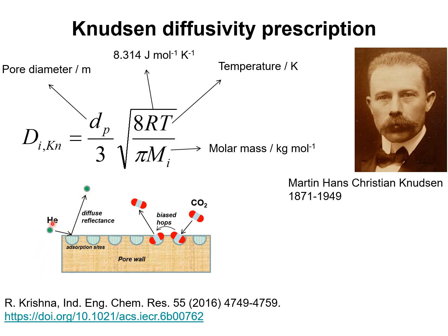This is true for practically non-adsorbing molecules such as helium. It is also true to a certain extent for hydrogen. A strongly adsorbed molecule such as CO2 will experience a situation that is somewhat different. As it strikes the wall, there will be a tendency to hop to a neighboring adsorption site before returning to the core region.